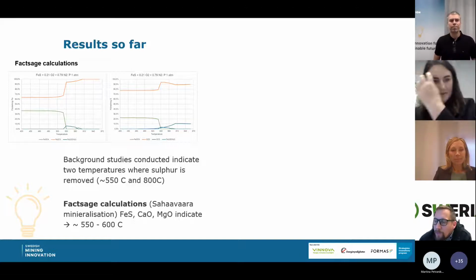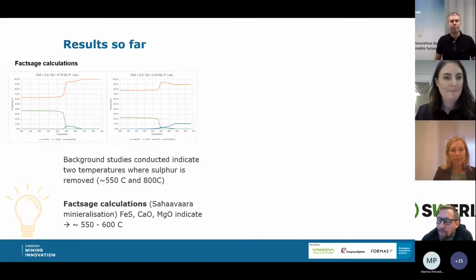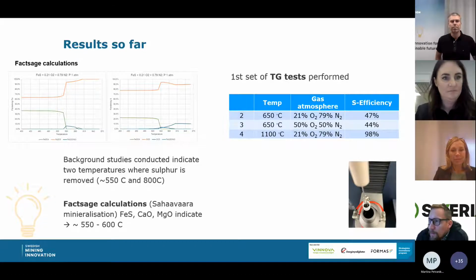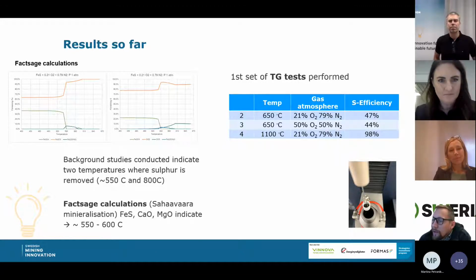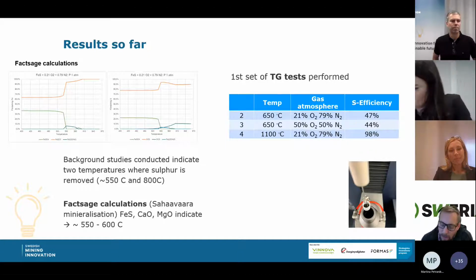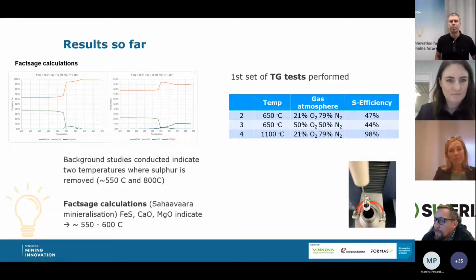In the initial studies, we have done some small-scale tests, and we have identified two sulfur peaks, one at around 500, which corresponds to the theoretical calculations, and one at a higher temperature. We also have done some TG tests, and based on these, we have been able to quantify that the first peak contains about 50% of the sulfur. And if we can run this up to, say, 1100 degrees, then almost 100% of the sulfur has been removed.